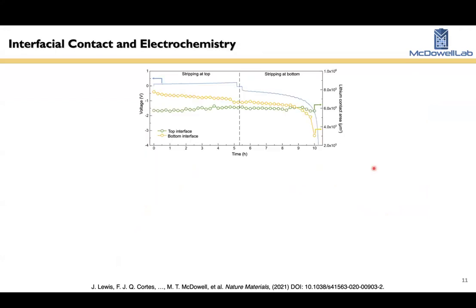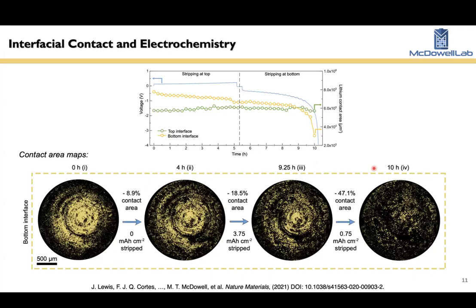So 3D views are cool, but actually I find it more useful to look at these projection images. These are what we call contact area maps. We're looking at a projected view of the whole interface, and the yellow pixels are pixels of contact. So when we lose the yellow, it means we're losing contact. The black pixels are lost contact at that position.